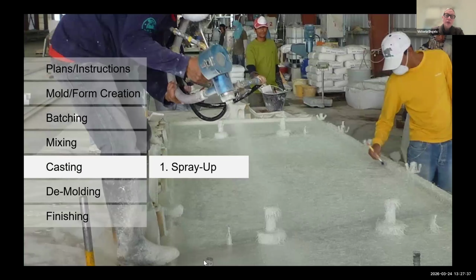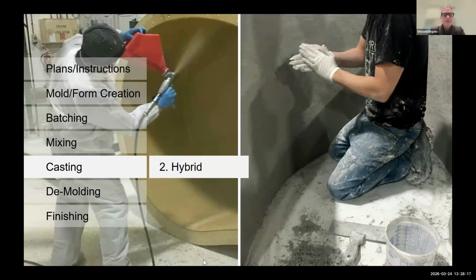GFRC can be cast using a few different methods. The methods employed depend on a few factors, including the shape and complexity of the piece being fabricated, the desired thickness, the skill level of the fabricator, and the tools at their disposal. One casting method is known as the spray up process. This is where the fabricator uses a chopper gun that mixes glass fiber from a spool with concrete while it's being sprayed into a form. The fabricator is going to take several passes, building up layer on layer to reach the desired thickness. And because longer fibers are used here, this method is going to produce a very strong piece.